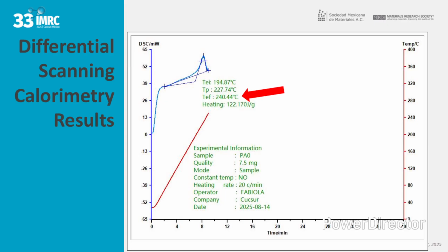The DSC analysis results show the material is in a glassy, rigid, and brittle state. Above 195 degrees Celsius, it enters a rubbery state, with greater chain mobility, flexible. The peak around 227 to 240 degrees Celsius corresponds to crystalline melting, Tm, not Tg. The Tg point on the graph is 195 degrees C, T equals 194.87 degrees Celsius, and is key because it indicates the minimum temperature at which the polymer begins to become processable